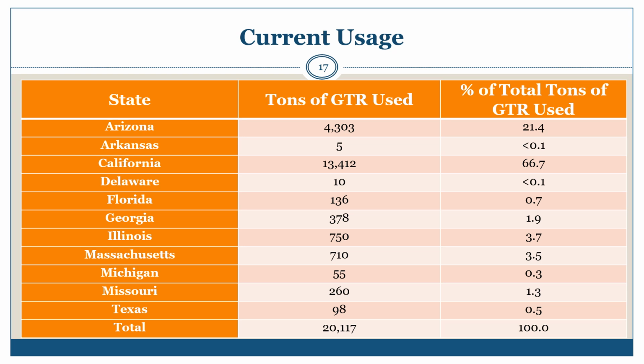California is by far the largest user of GTR modified asphalt binder, with uses being directed by PRC 42703. The California DOT, Caltrans, requires that GTR be derived from automobile and truck tires only, that GTR binders be homogeneous, that GTR modified binders may not contain visible rubber particles, and that GTR modified binders contain a minimum of 10% GTR.